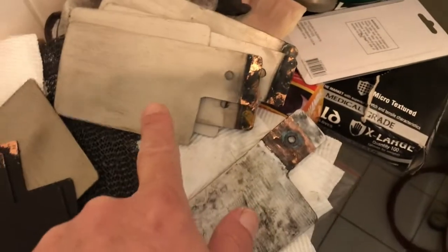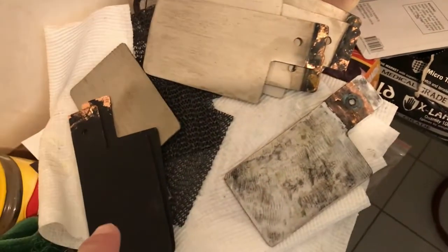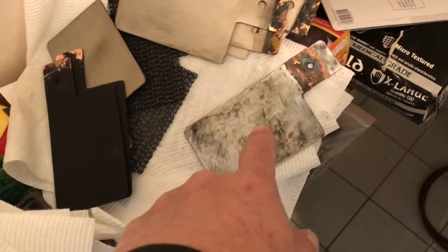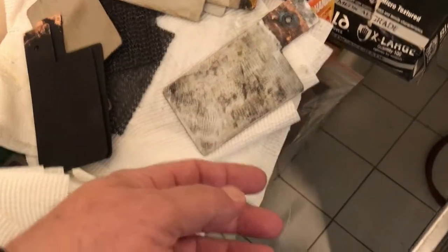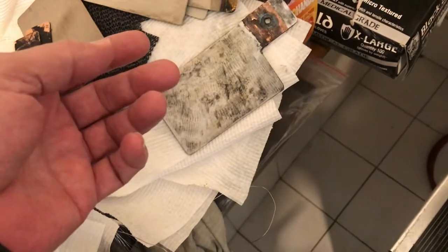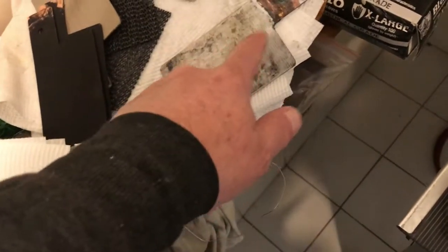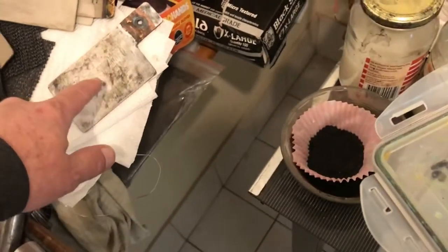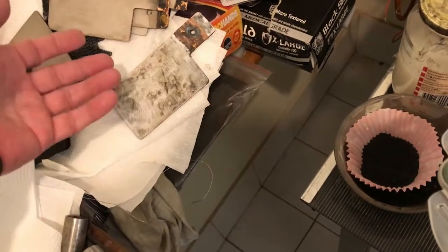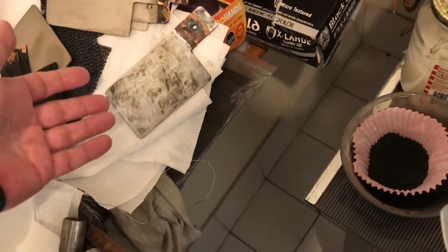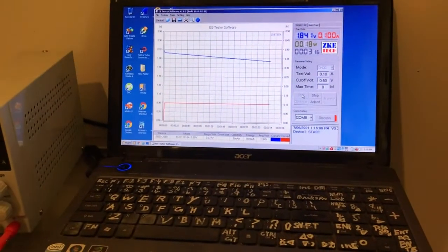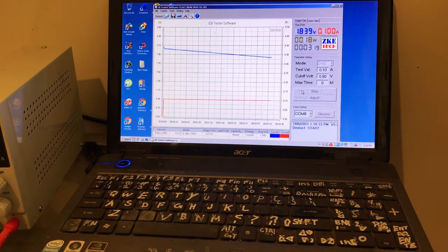I have some new electrodes I've coated. Got some on the go, one failed again. So I'm having trouble with my nickel acetate. It keeps turning black after about 40 hours of plating. I think it's from the copper plating. The vinegar must really eat out of it, because this one was in there at 20 milliamps overnight, and then it dropped right down for some reason, and in the morning the copper was removed and there was only a little bit of plating of nickel. So you have to have about 100 milliamps or so, or 80, to beat the dissolving of the copper.